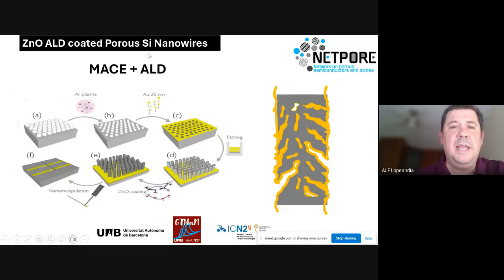oxide. Zinc oxide ALD is a conformal deposition technique, and then it will go inside. This is not gold. This is zinc oxide. Sorry, I used a very bad color that I just realized. This is zinc oxide going inside of the pores and trying to fill as much as possible the porous materials.